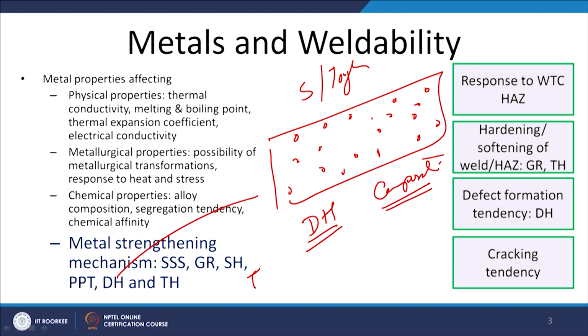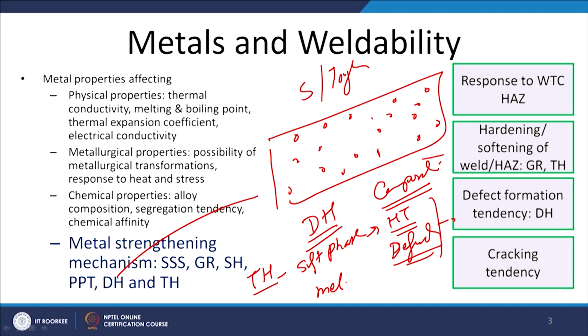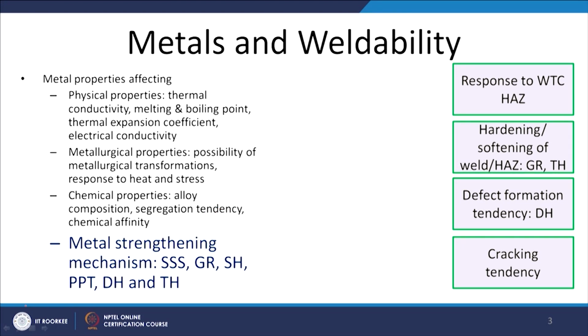And then transformation hardening, where in general the material has soft phases, but when it is subjected to a controlled heat treatment cycle or controlled deformation cycles, certain metallurgical transformations take place, which lead to an increase or change in properties of the material for strengthening purposes. So, in transformation hardening, basically the soft phases undergo controlled heating followed by cooling, leading to the formation of suitable metallurgical transformations for strengthening of the metal. So, these were the strengthening mechanisms and the way by which they work.